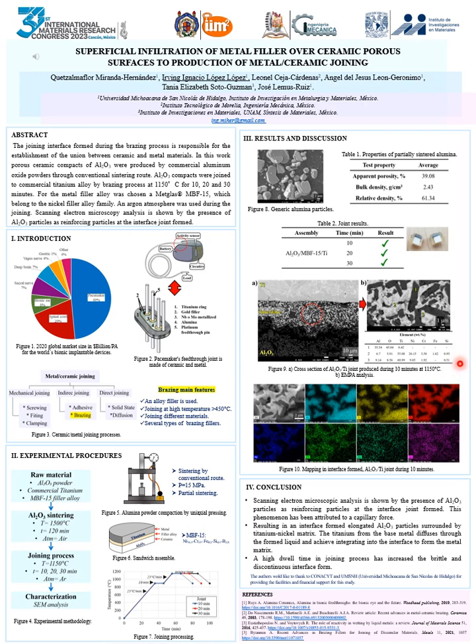The presence of elongated grains of aluminum oxide surrounded by a metallic matrix was observed through elemental mapping using scanning electron microscope. When the MBF15 filler alloy reached the liquid state during the joining process, it infiltrated between the pores of the ceramic. In addition, this phenomenon may have stimulated the participation of titanium as an active element. The formation of the metallic matrix of the interface was aided by the filler alloy elements nickel, chromium, and silicon.